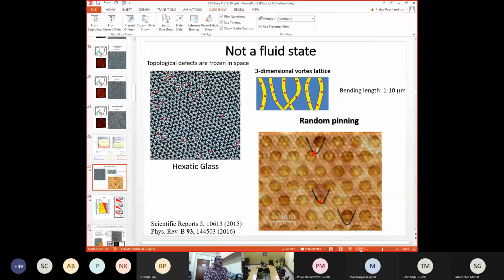But then we took this image, let's say here, and staying at the same temperature, the same magnetic field, at the same position, we kept on scanning for 24 hours. So this is a spectacular technical achievement for our system, that we can stay exactly at the same point for hours at ends and actually for days. So when we took this, we took an image every hour for 24 hours.